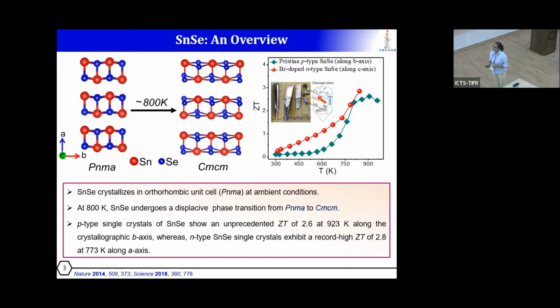Because of the layered nature of the crystal structure, it has highly anisotropic properties along all three crystallographic directions. In 2014, single crystals of SnSe created a sensation in the thermoelectric community, as they showed a record high zT of 2.6 along the crystallographic b direction. In subsequent years, n-type single crystals have also shown a very high zT of 2.8 along the crystallographic a axis. But the problem with single crystals is that they are really difficult to synthesize, and thus they cannot be used in practical thermoelectric applications.